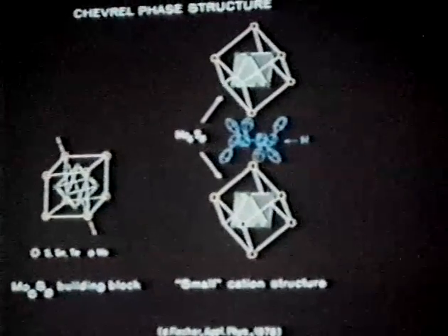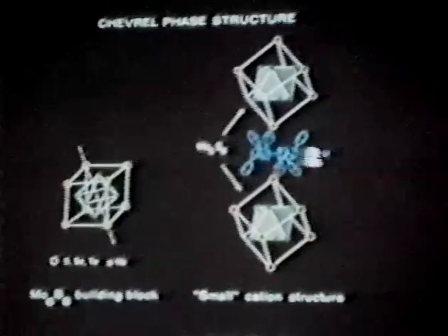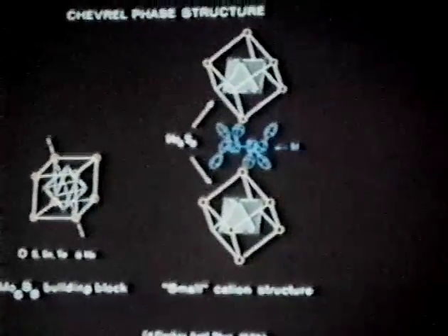For the small cation structures, you actually form channels in which you can put the small cations, and these are somewhat delocalized. The thermal motion involved indicates that you can consider these really channels in the structure. And this probably is the reason why you can introduce various stoichiometries into the Chevrel phase compounds. However, when you get up to the large cation materials, you don't have that opportunity anymore.